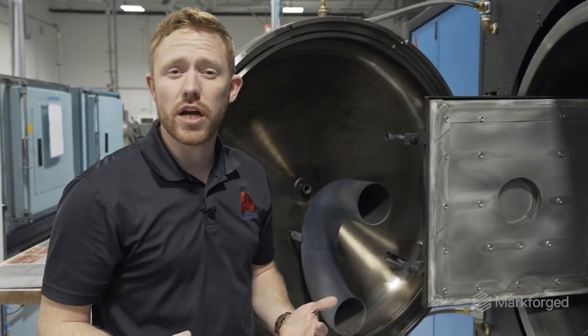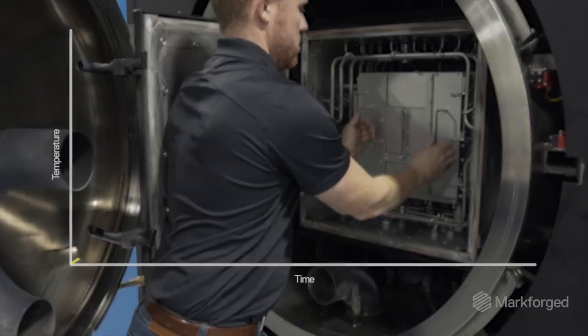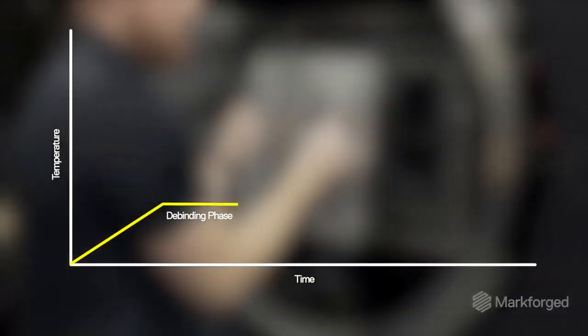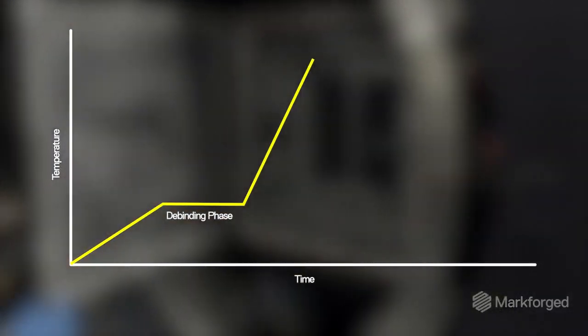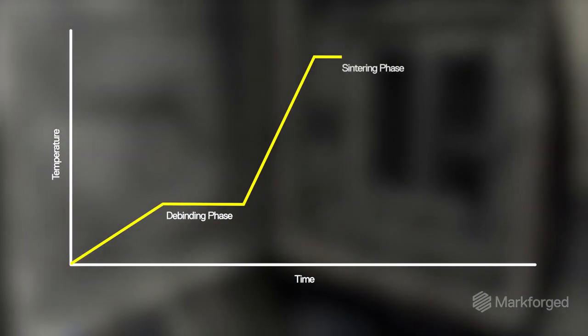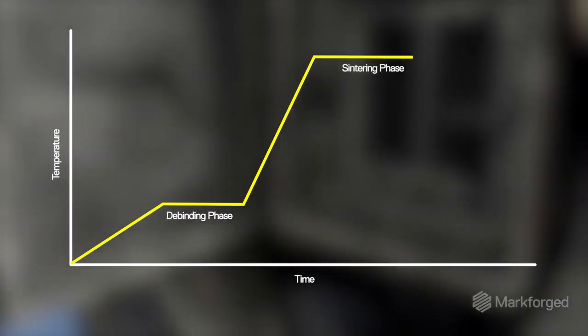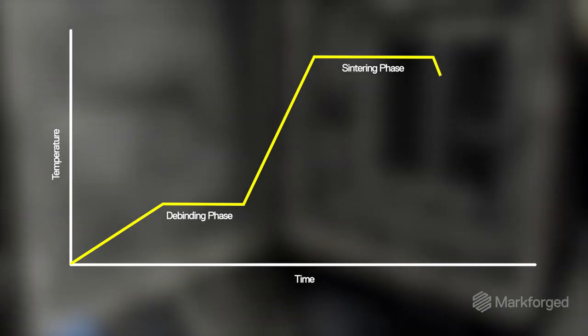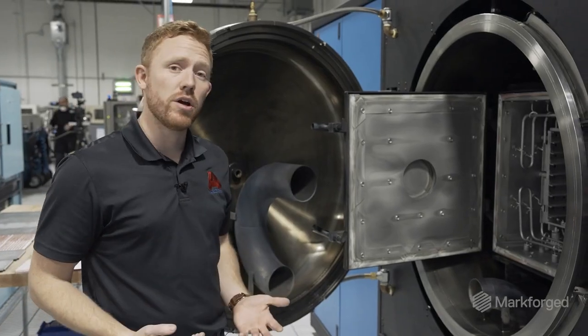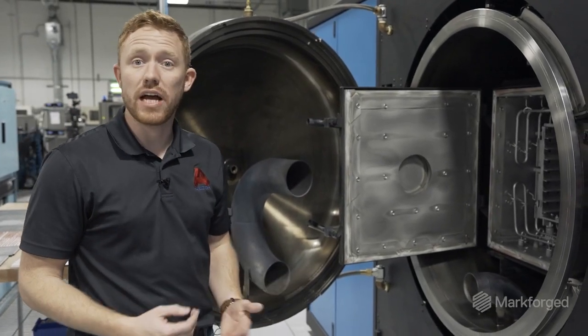It's about a 20-hour cycle. The first segment, we remove the binders from the part. The next segment, we ramp up to near top temperature and hold for a prescribed amount of time. The parts will shrink roughly 20% in each direction, and then we'll cool down. At that point, the parts are ready for their next operation.